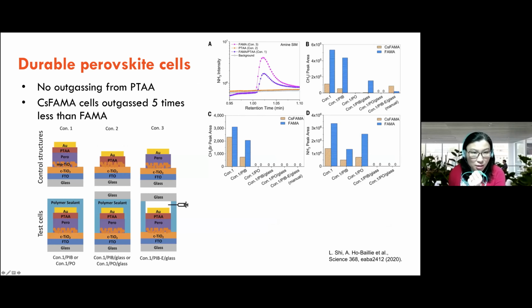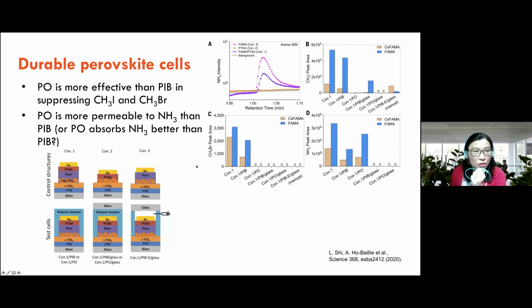Then we stress the test structure as well as the encapsulated cell. You see the test structure here without the encapsulant, and then the full cell with the blanket encapsulation and the edge seal, the void. So we can see two things. PTAA, which is the HTM of the cell, is quite stable. There's no outgassing. And cesium FAMA outgasses 5 times less than FAMA. So what do we find?